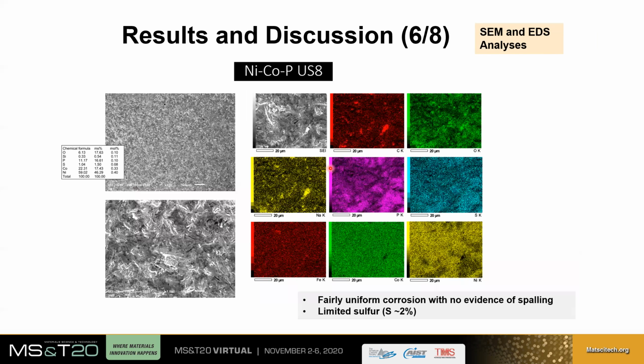If we are looking at the next coating here, the electrolytic nickel cobalt phosphorus coating, we don't see the coating peeling off, falling off. We see a more uniform corrosion. And we see a little bit of sulfur intake. I mean, for the electrolysis nickel, we saw almost no sulfur intake. For the QPQ, we saw 30%. Here we see 1%, and it appears to be very uniformly distributed. Okay, but what is important to see, there is no spalling.